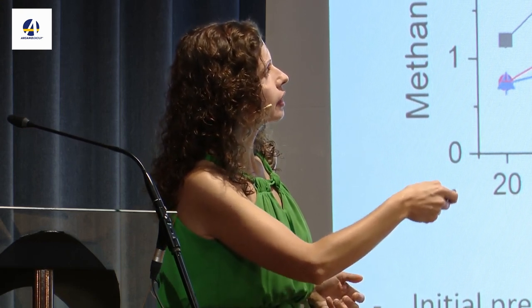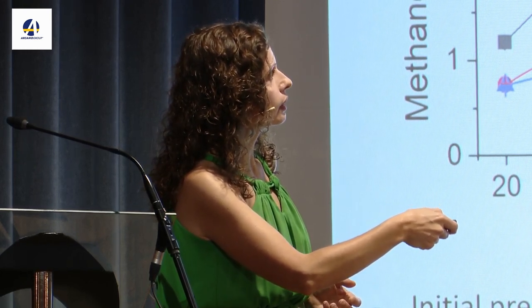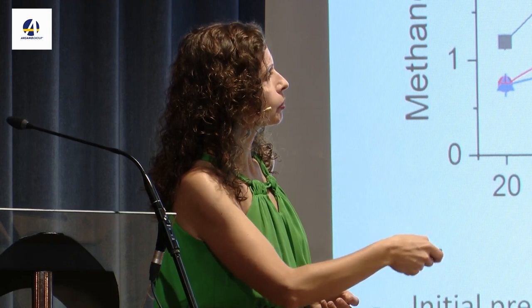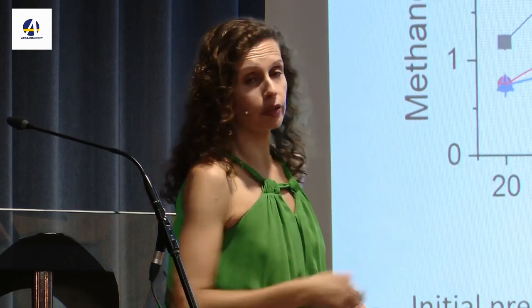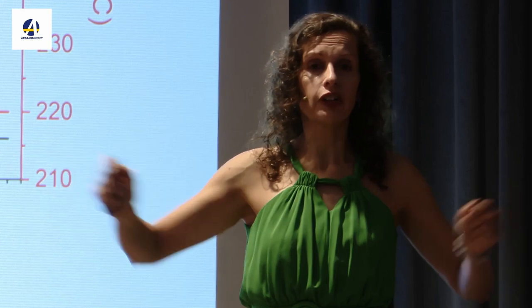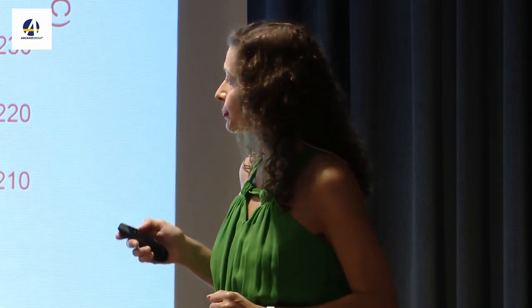But if you go higher in temperature, in this case 280 Celsius, you start seeing the deactivation. And this deactivation we can spectroscopically assign to the formation of brass. So keep in mind that there was a lot of discussion also if the deactivation was due to sintering. Here, in these particles, we see both sintering and the formation of brass. But in the small micellar particles that I could put farther away apart from each other, there was no sintering after the reaction. And still, I saw the deactivation when I was making the brass.